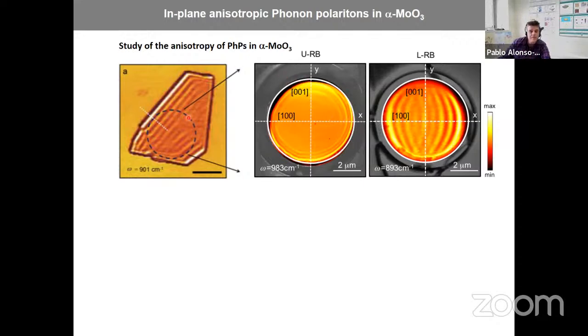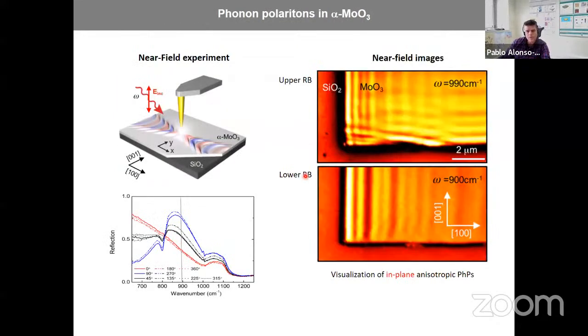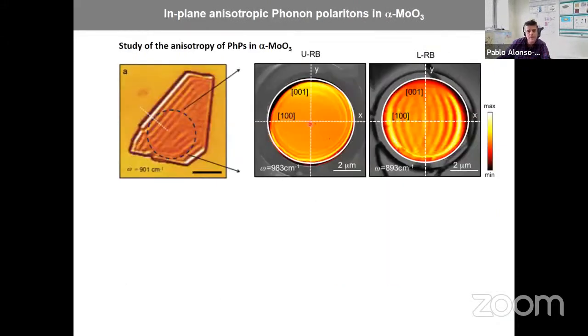And for the first frequencies where we saw this kind of anisotropic propagation, we saw this pattern. It's an elliptical pattern. And in the other frequency, we saw this kind of almond-shaped pattern, where there are fringes coming back to the tip when they are launched, almost in all directions, but not, for example, in this direction.